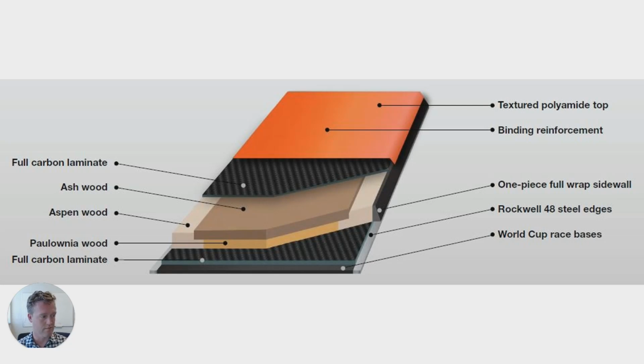I apologize for the low-res image, but you can see that we still have wood. We've got ash wood in there, we've got aspen wood, we've got different woods inside of there. We've got carbon fiber, we have top sheets, sidewalls, bottom sheets, we have all sorts of stuff. So really, there are all these layers. We've got reinforcement layers, so they enhance the strength, the torsional stiffness, and the edge hold. They can use fiberglass, carbon fiber, metal laminates, aramid fibers like Kevlar, basalt fibers.